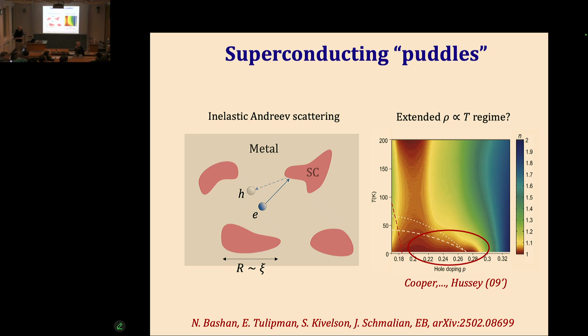Thank you. In cuprates, around 20%, the T-linear regime famously extends up to very high temperature. How do you think about that? So indeed, over here, this behavior can extend to 1,000 Kelvin. I don't believe that this mechanism operates at 1,000 Kelvin. So if this picture is correct, that somehow means that the linear in T in overdoped at low temperature and the linear in T at 20% at very high temperature have a different origin. So I would have to say that somehow this and this have a different cause.